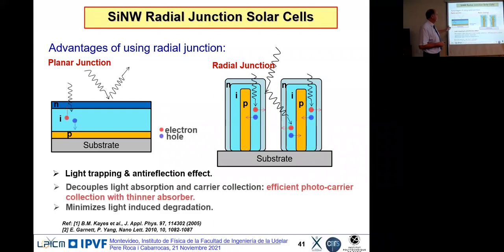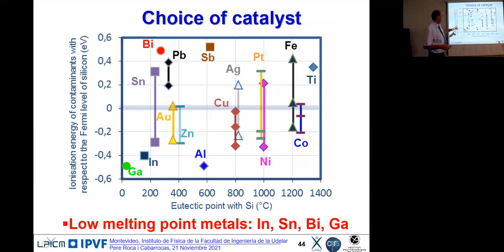And the question was why we choose low melting point metals, because we are at low temperature. Gold is about 400 degrees. People use gold, iron, metals for which you need 1,000 degrees. I cannot afford 1,000. It's interesting, but if I want to do something on glass, low cost, maybe it's not a good way. So we focused on tin, which doesn't introduce, unlike gold, defects in silicon. So definitely it's good for understanding things, but for practical applications, it will be more difficult. And then that's why we use gallium and indium, which are low temperature. That could work, but it will be more difficult to keep it stable.